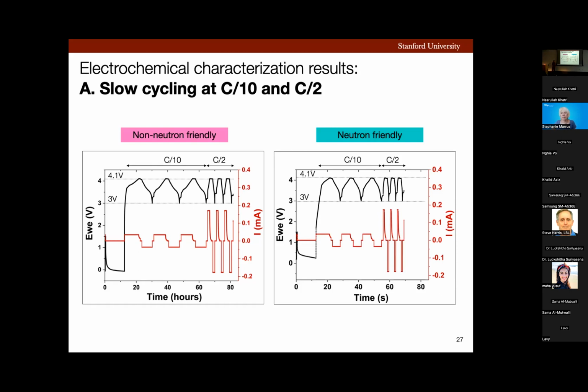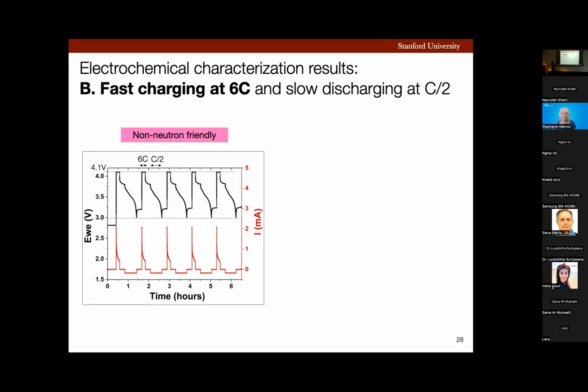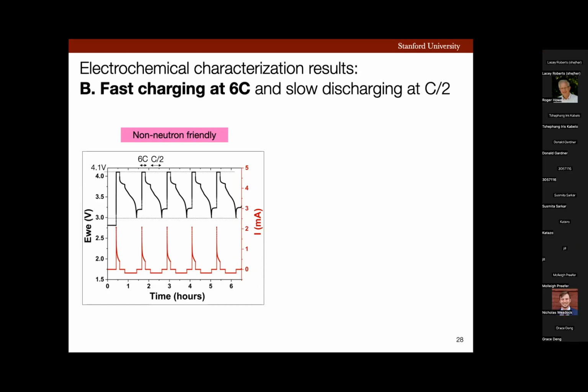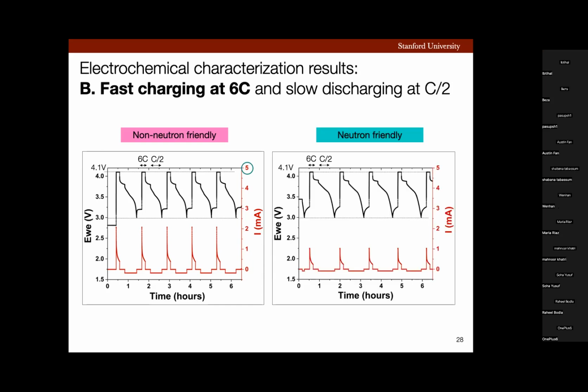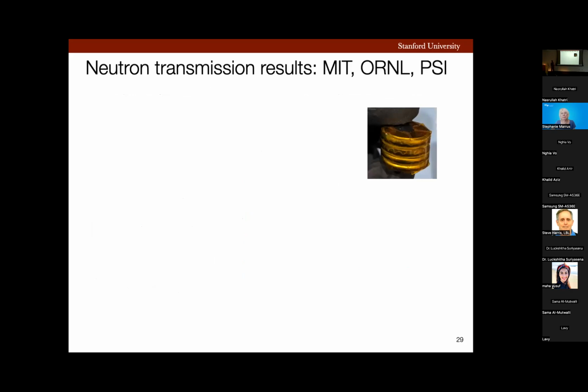Now let's see how the battery performs under fast cycling at 6C, which is 10 minutes of charging. And by 10 minutes, you would notice here the current relative to the current given in slow charging is pretty high. So this battery was cycled between 3 and 4.1 volts at 6C and then discharged at C/2. And this signature corresponds to that of a standard battery. Now let's compare the signature of my neutron-friendly battery. Again, the two signatures look very similar to each other, which means that my battery is capable of fast charging at 6C. And once I was content with the electrochemical performance of my battery, I proceeded with the neutron transmission